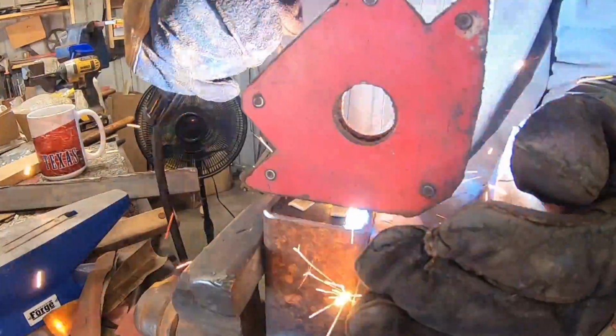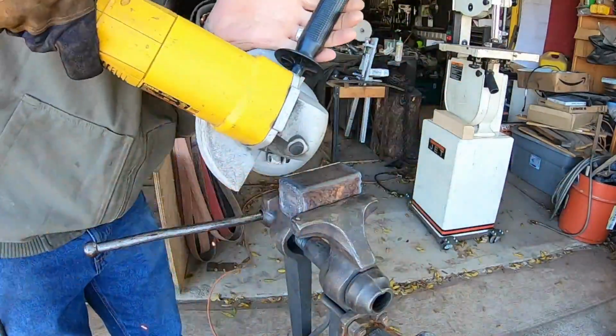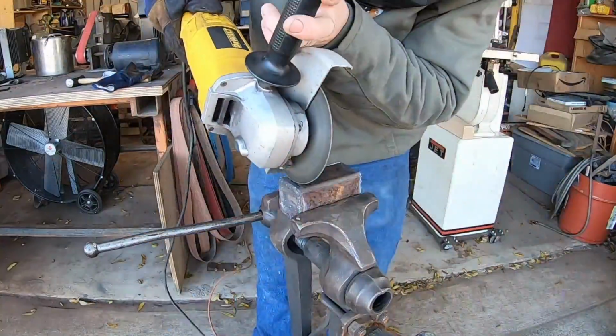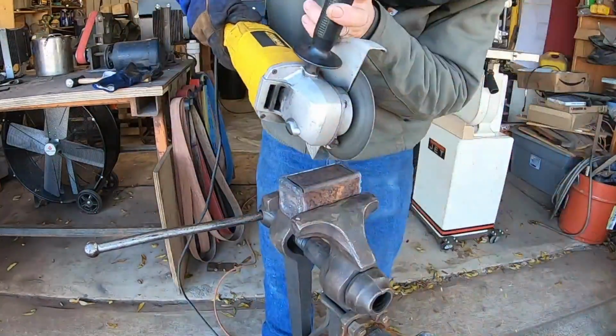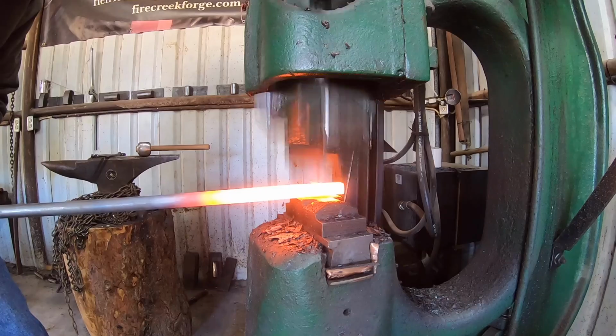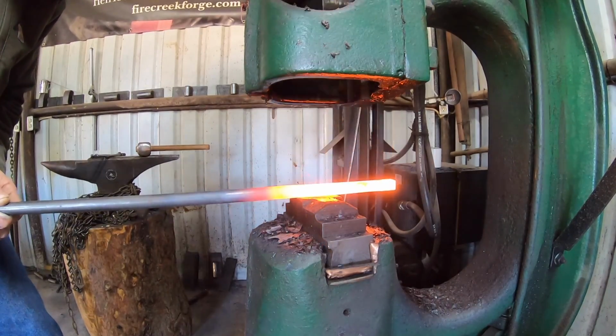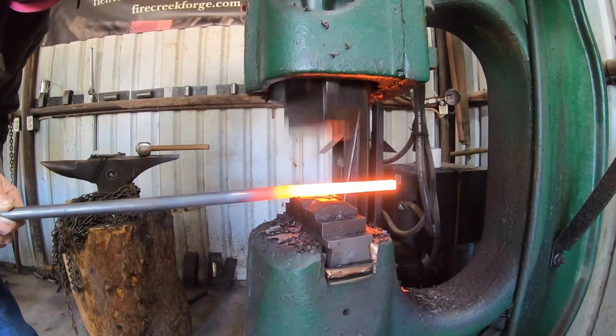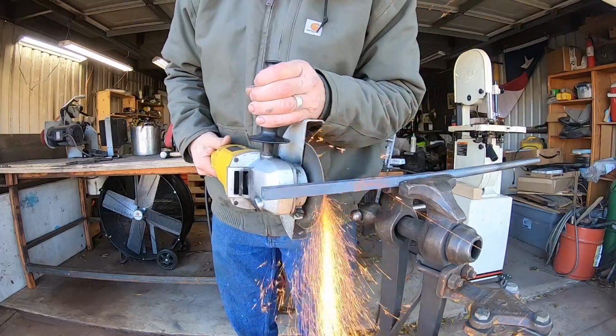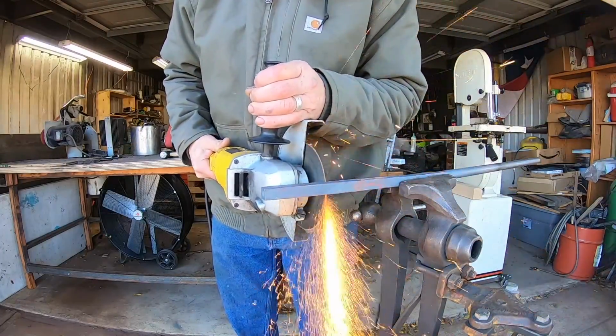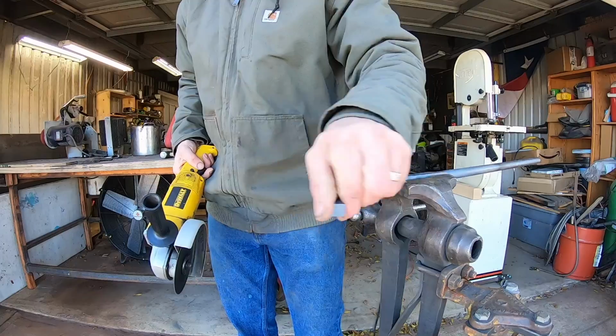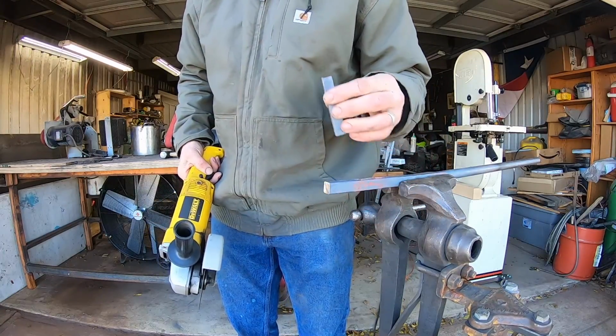So I'm welding up the caps on both ends of the can here and then cutting out the top of the canister. The inside will be coated in white paint. That'll keep the contents from welding to the can. Part of the constituents of this canister is going to be some 52-100 steel, excellent blade steel, excellent edge steel, which is what it's going to be in this case, the edge of our knife.